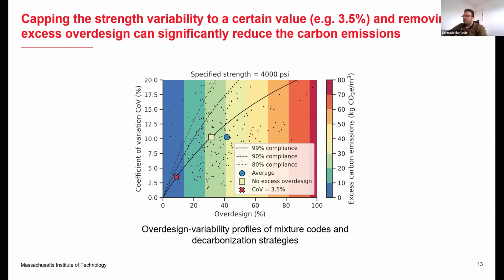Here, we developed an overdesign versus coefficient of variation space, and we wanted to show the excess carbon emissions in this space. Each dot represents a mix code in industry, and we have compared the average overdesign and coefficient of variation with 99% compliance according to ACI, and no excess overdesign. So for 4000 psi here, we can see that there is a gap between the average and the no excess overdesign dot that represents an opportunity to reduce the overdesign, but keep the safe margin up to 99% compliance.